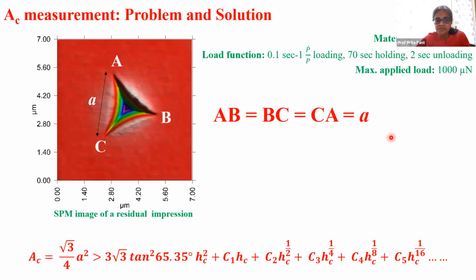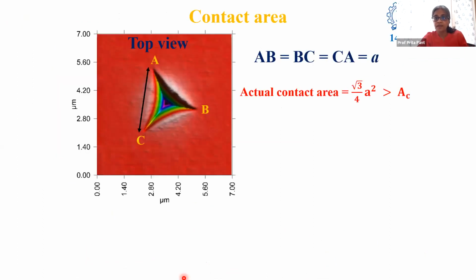And what we found is that if I use this measured length A, the contact area that I calculate like this using the geometry is actually greater than the area that I was earlier calculating using the contact depth that I had got from my previous measurements. So there is some problem in taking the standard method and applying it to it. These two don't match up. Okay, that's what it took us a while to get to. So here is the same figure again, that the actual contact area is greater than AC. And that turned out to be the source of our troubles.